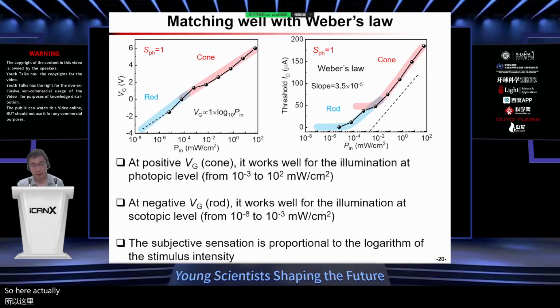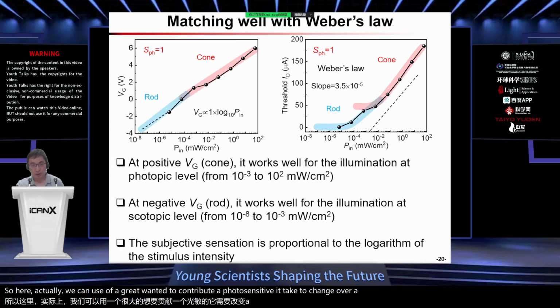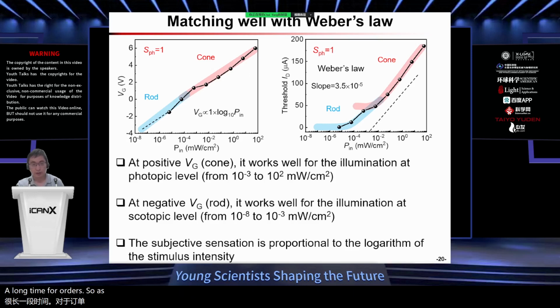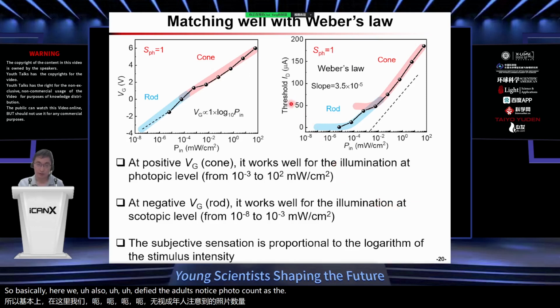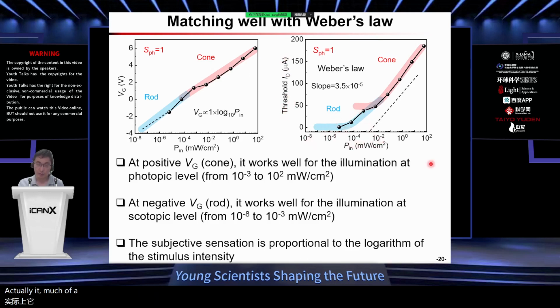So here we can use a gate voltage to control its photosensitivity to change over many orders of magnitude. At positive gate voltage, the same device works like a cone cell. But if we use a negative gate voltage, the device works like a rod cell. There is a very famous law, the Weber-Fechner law. It defines the relationship between the external stimulation and the inside perception. Here we also define the just-noticeable photocurrent as the threshold. We plot the threshold as a function of the light intensity, and it matches very well with the Weber-Fechner law.